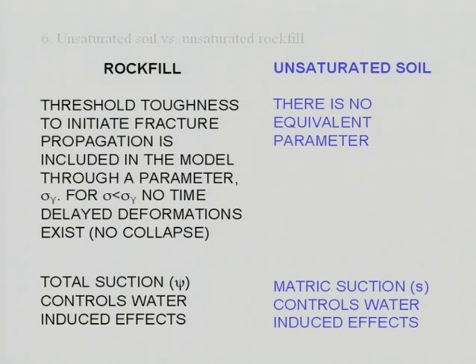Now, in a rock fill, there exists a threshold toughness, and this comes from the underlying subcritical crack propagation theory. And we included that very simply through a stress parameter. We may do other things, but I think we should keep in mind that below some stress, nothing will happen. There is no such equivalent concept in soils. Now, total suction controls water-induced effects. However, in soils, at least in well-behaved unsaturated soils, such as silt or low plasticity clays, in general, matrix suction controls water-induced effects. I always joke saying that, if you have an acid rain, it will induce a smaller collapse than a true, clean rain. Perhaps it's the only good effect of an acid rain.